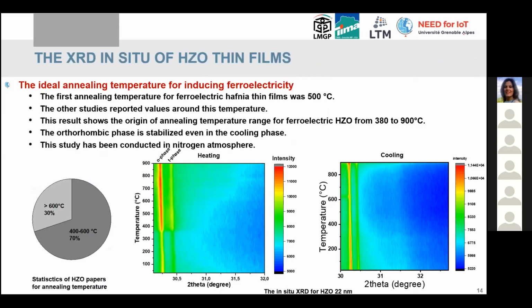The second result is that in the literature the most used temperature for annealing is between 400 and 600. So we have conducted an in situ X-ray diffraction for higher temperatures, from room temperature to 900 degrees Celsius. And here we have found that the appearance of the structural signature of ferroelectricity, the orthorhombic phase, started below 400 degrees, and it stayed stable until 900 degrees. So this result reflects the compatibility with the CMOS back-end process.